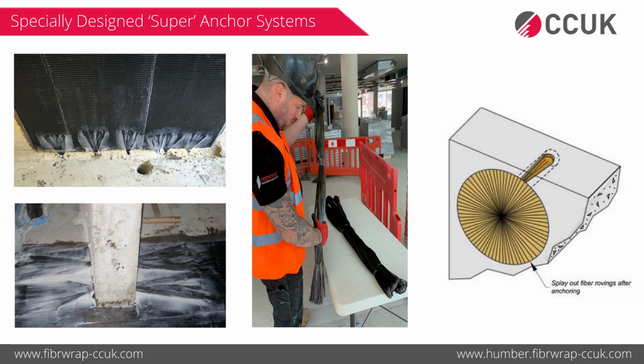So that's how these nominal anchors are used, which are mainly to provide further assurance against the debonding and delamination failure. Then we have these bigger anchors, which you could see the guy holding in the hand in the middle image. They are called super anchors. They're specially designed anchors which are designed for a particular force. These are the anchors which are used in the column testing as well. Whenever we are designing carbon fiber, we know the force in the FRP in that particular location, and if there is an obstruction in the way, we can use these anchors to transfer strengthening from one side to another side. The same thing we did in the column as well. We knew the push out force in terms of the load and everything. That force we wanted the anchor to resist, and that's how these anchors were designed.